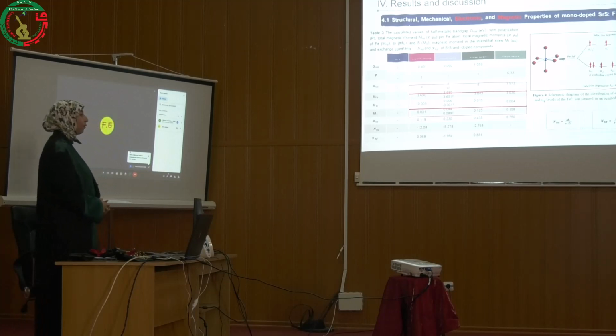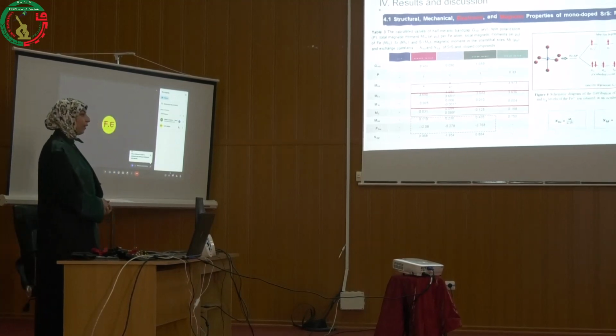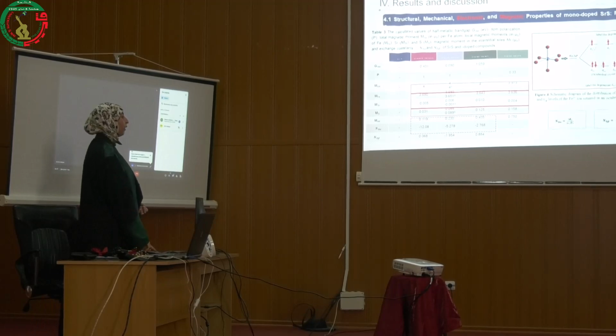Also, the exchange constants are calculated using these two formulas. The exchange constant between s and d states is found to be negative, indicating an antiferromagnetic interaction, whereas between p and d states it gathers both positive and negative signs, indicating ferromagnetic and antiferromagnetic interactions respectively.